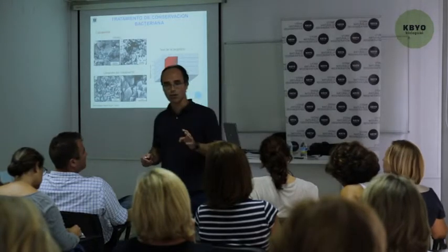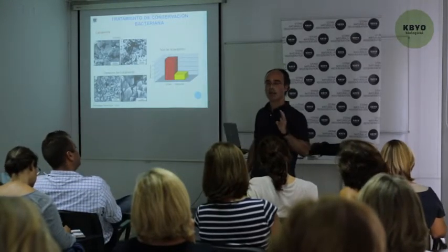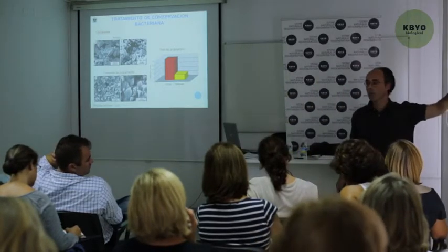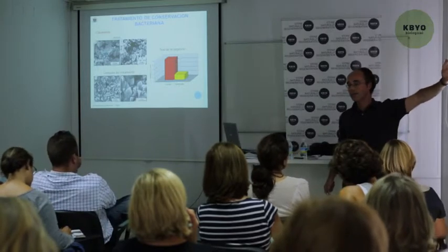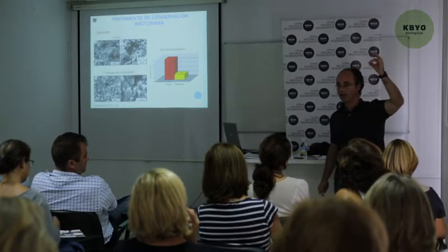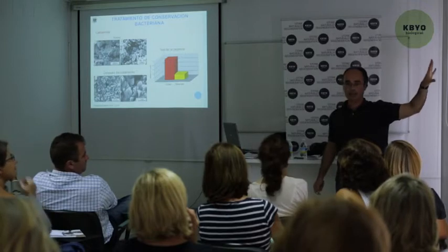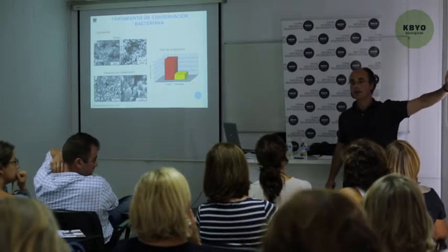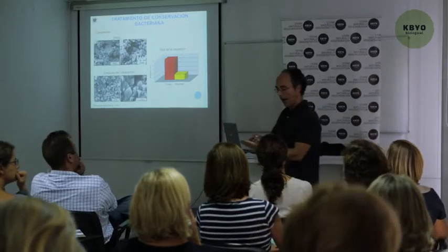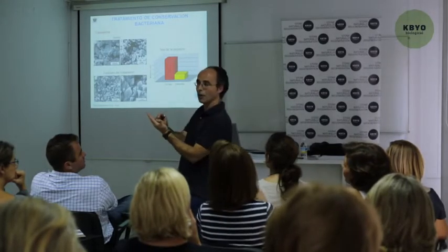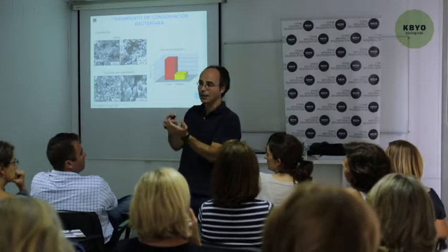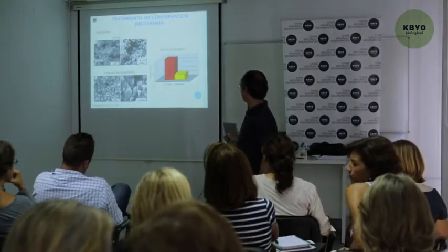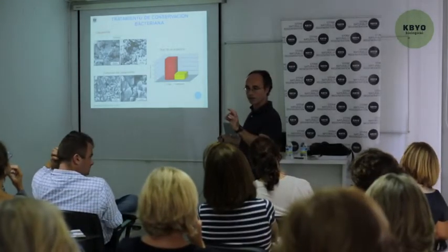Here, we see quantitatively that the material before the treatment loses powder or superficial grains, and after the treatment, the quantity lost reduces to a fifth. So, we can conclude that the treatment is very effective. Later on, we will see that there are other tests to evaluate the efficiency and to measure the resistance. Also, we can test in the laboratory the resistance to a bath of ultrasounds to see how much quantity of material gets lost with this method. Before treating, here we see the big quantity of lost material, and after the treatment, the loss of material is reduced a lot.